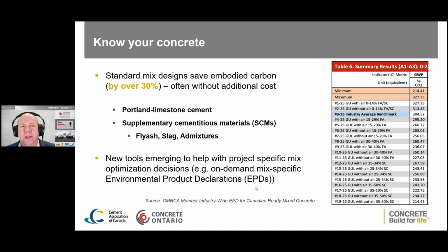Back in 2016, the Canadian Ready Mix Concrete Association started off with our first industry average EPD for ready mix concrete. So we went through 18 different mix designs. We basically looked at, for a sample mix design with different levels of either GU or GUL cement and varying levels of supplementary cementing materials, what is the impact that has on the carbon content of the material? So picking an example here, this is just 25 MPa concrete pulled out of the existing document. You see the lowest carbon content is at 214 kgs per cubic meter, and the highest is at 327.